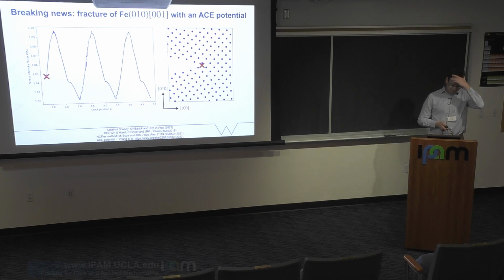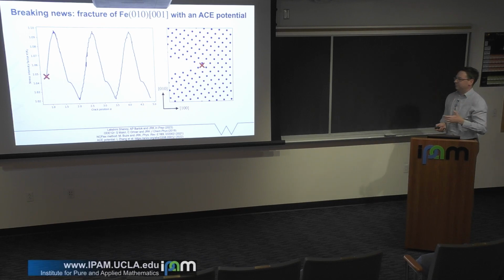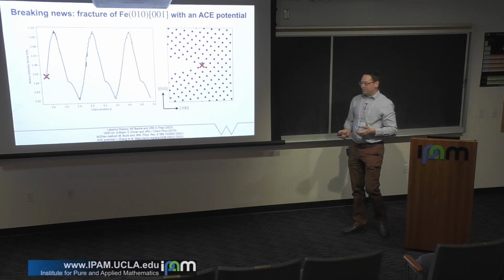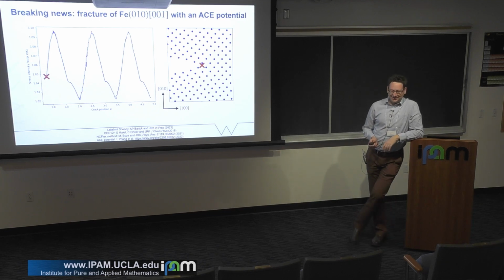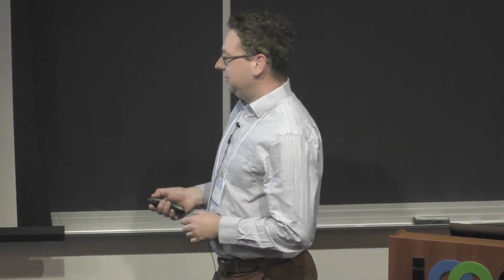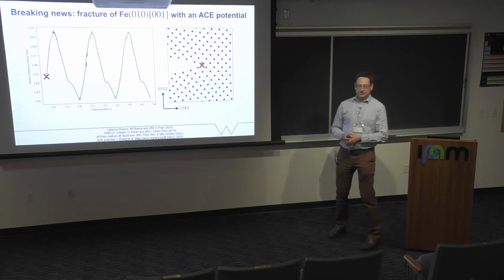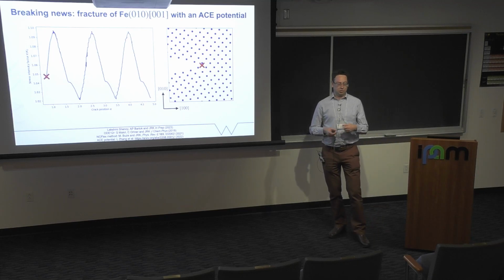Okay, so I couldn't resist showing you some, pun intended, breaking news, where we've extended this approach to a more realistic materials model. So this is iron. You don't think of iron as a brittle material, but at low temperatures it is, and that's a big problem. There's a brittle ductile transition below which you're at risk of getting fracture, and that's relevant for civil nuclear reactors, for example. This is using a machine learning potential, rather than the previous results I showed you, which used quite a simplified potential, albeit one that does give a brittle response.